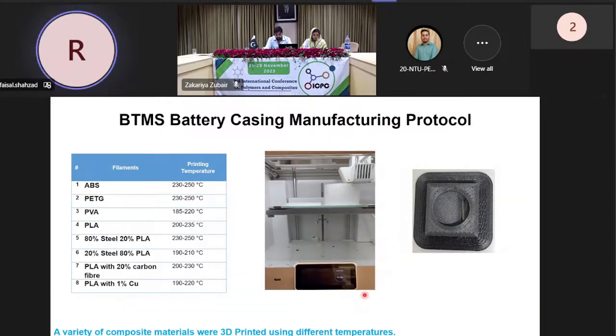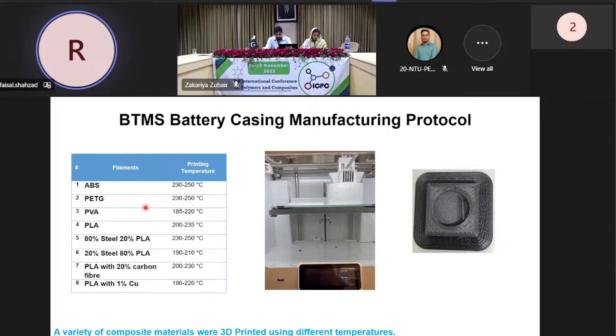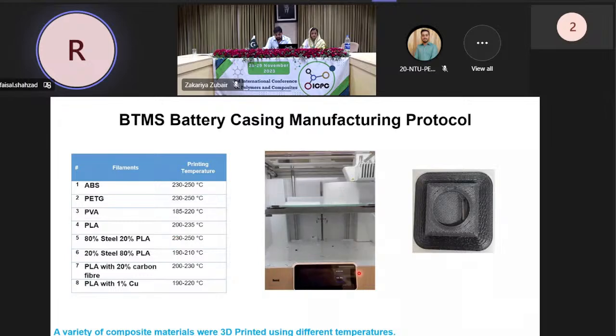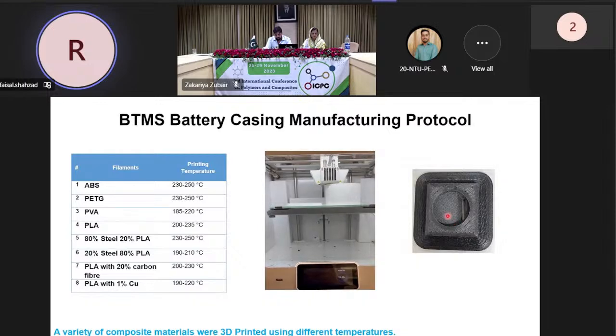Then the next stage is the printing. We have optimized, because ABS, PETG, PVA, and PLA have a fixed temperature at which we can print. But we have a mix of 80% stainless steel with 20% PLA, and 20% steel and 80% PLA. So we have optimized the temperature at which we can print these filaments. If we print at the normal temperature, we can't make it, because the printing will stop and it will be more porous compared to normal printing. So you can see this is the Ultimaker, and it's printing the battery pack.